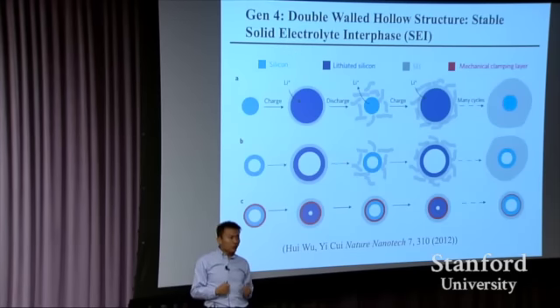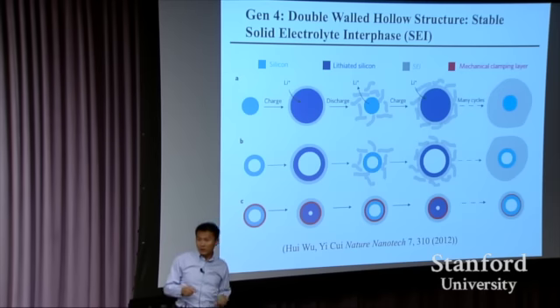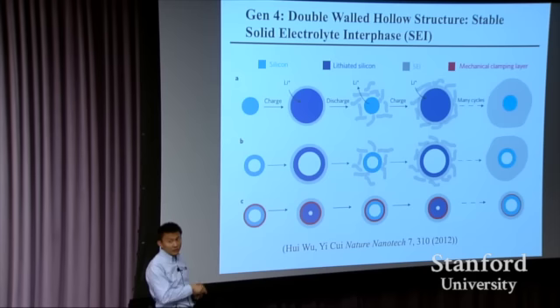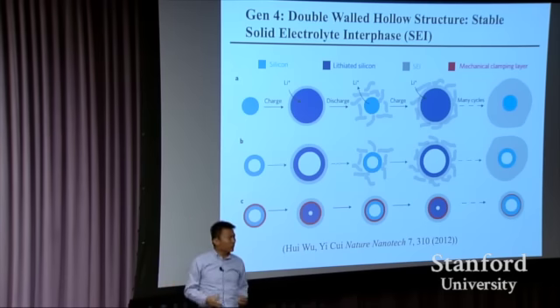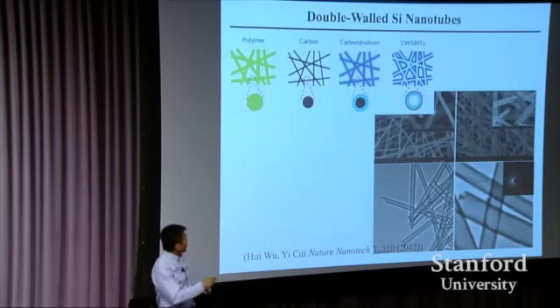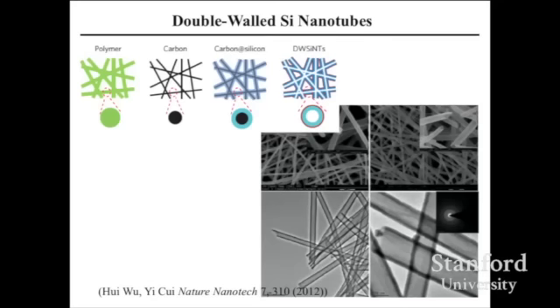Now silicon starts to think about where it should go, towards outside or inside. But the outside is so strong, it's constrained. It has no choice. It better go towards the inside. So the outer surface is never moving, facing the electrolyte. Even though the inside is going crazy, the outer surface never feels that. That's exactly the idea we came up with. And we started to make a double wall silicon nanotube. It goes through a process, I don't need to go into the detail. Eventually what we make is silicon inside, silicon dioxide outside. These are the hollow double wall nanotubes you see.